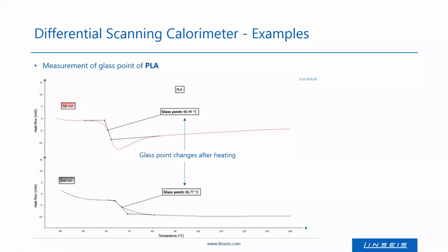Here you can see a measurement of the glass point of PLA. What is important from these curves is that the properties of the PLA change during heating, so to say. In the first run, the glass point is at roughly 60.5 degrees Celsius, and after the sample cooled down and was heated again, the glass point changes to around 67 degrees Celsius.